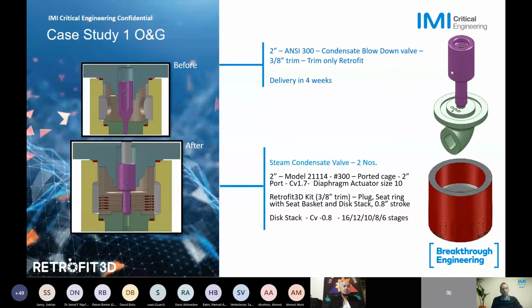So we eliminated the impact on the bonnet, we protected the valve body from negative impact, and we included up to 16 stages of drag in this trim to control the velocity at any given stage in that control valve. So that's just one way on how it can be addressed. And obviously, at the same time we were looking at the flow conditions and adjusting the capacities to make sure that this plant sees the maximum benefits from the new trim.